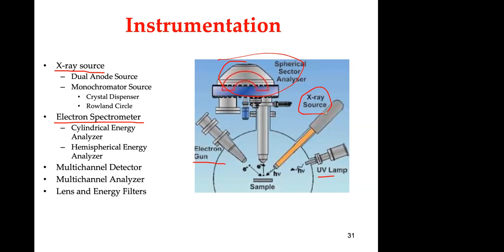I mean, you can do Auger with an X-ray source, but also with an electron gun. Electron guns might be used for Auger, but also electron guns sometimes use low energy electrons, probably five electron volt energy, very low energy. And it's just to compensate for the charge that is formed on the surface.